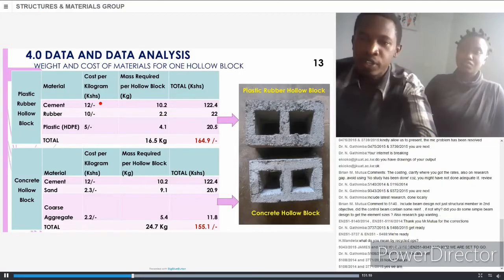So based on the unit weight of the hollow blocks, we did a comparison of concrete hollow blocks and the plastic rubber hollow block. The plastic rubber one weighed 16.5 kilograms and the concrete hollow block weighed 24.7 kilograms. And when we evaluated the cost of each constituent material, we got 164 shillings for the plastic rubber and 155 for the concrete hollow block.